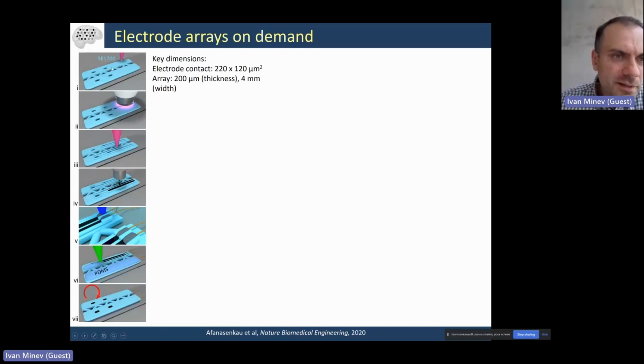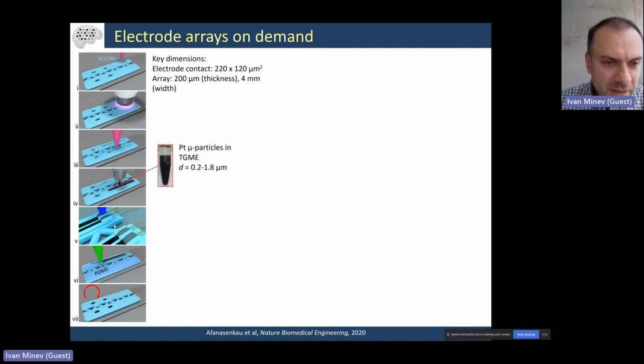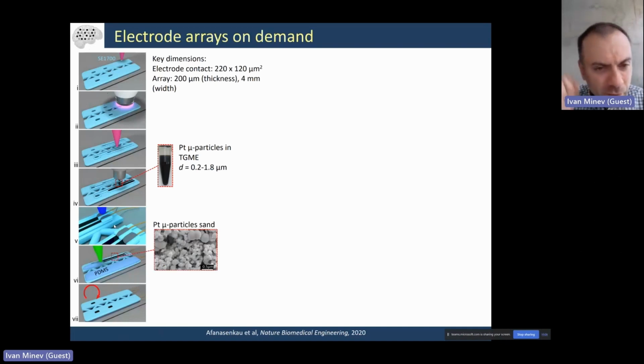We use the shear thinning silicone to produce the insulating parts of the electrode array, and then we use the inkjet functionality to fill the channels with conductive inks. In our case, we use a two-step process of forming the conductive ink. We use a dispersion of platinum nanoparticles in a solvent, and we jet this into the channels, and then we evaporate the solvent. So this creates, in a way, a platinum sand of microparticles inside these grooves.